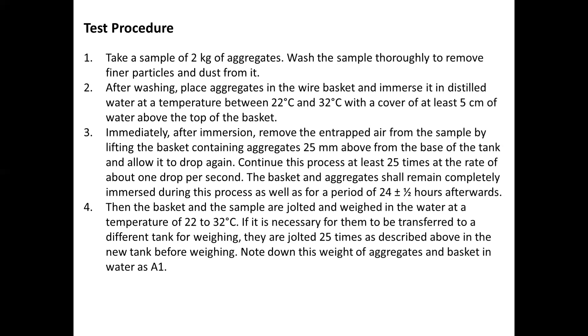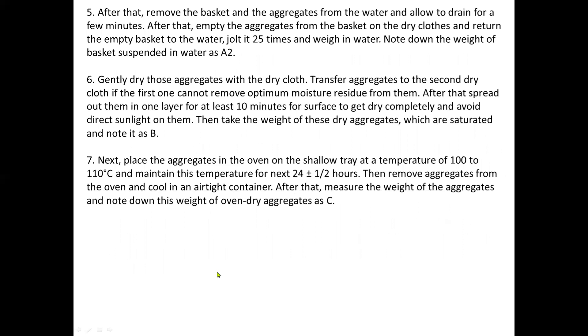Then the basket and sample are jolted and weighed in water at a temperature of 22 to 32 degrees Celsius. If it is necessary to transfer them to a different tank for weighing, they are jolted 25 times in the new tank before weighing. Note down this weight of the basket and aggregates in water as A1. After that, remove the basket and aggregates from the water and allow it to drain for a few minutes. Empty the aggregates from the basket onto a dry cloth, return the empty basket to the water, jolt 25 times, and weigh in water. Note down the weight of the basket suspended in water as A2. Gently dry the aggregates with a dry cloth and transfer them to the second dry cloth if the first cannot remove optimum moisture residue from them.